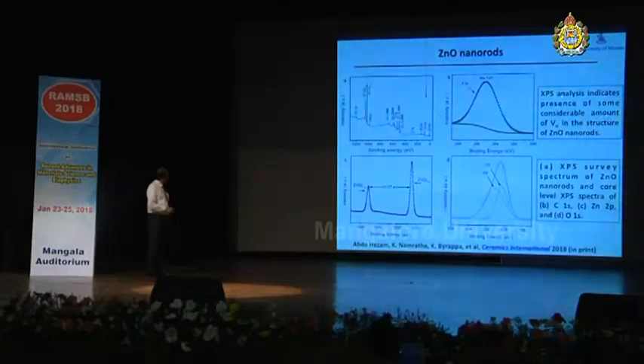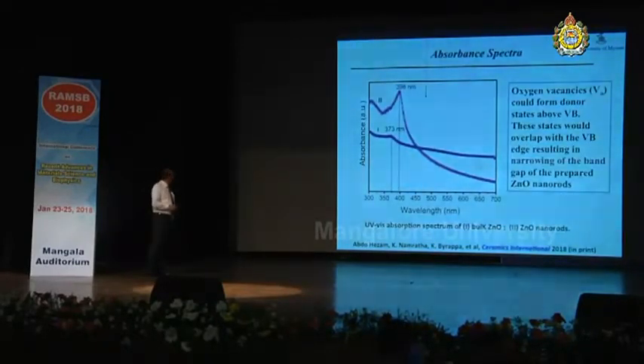You can see here, and this indicates the presence of some considerable amount of oxygen vacancies in these zinc oxide nano rods. And there are various interpretations nowadays with respect to the oxygen deficiencies. Some people believe that the higher photocatalytic activity is because of the increased oxygen vacancies, and some people do not believe that. They give some other reasons.